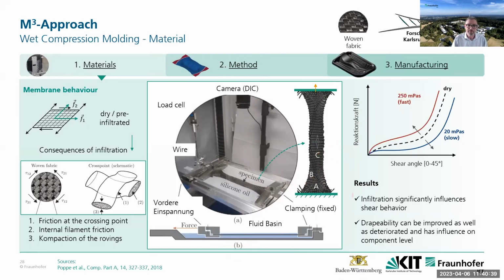bias extension test. And finally, the drape behavior, and that's what you can see here nicely, can be improved as well as be deteriorated compared to a dry fabric, which is very important for the process and the mold design. So it has to do obviously a lot with the viscosity and the reactivity of the resin, which is the viscosity over time.